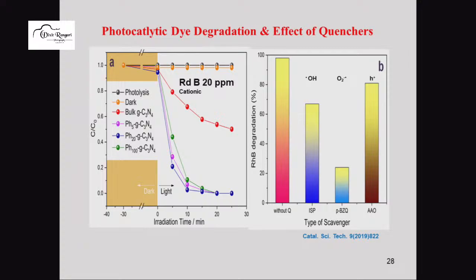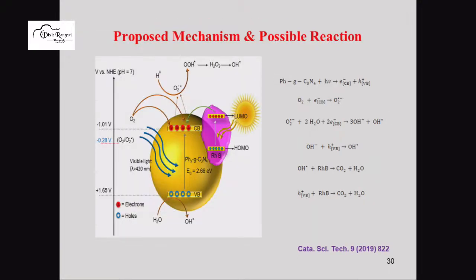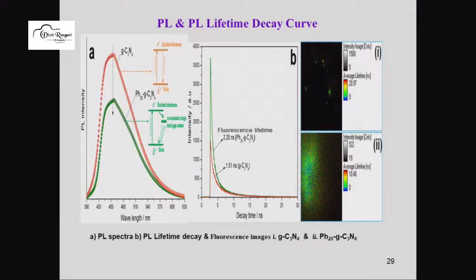And what are the species? The photocatalytic process involves different species: the electron, hole, hydroxyl radical, and superoxide ion. What are the species responsible for the degradation of these dyes? That can be determined by the quencher experiment, and this quencher experiment shows the presence of the superoxide ion as the major species for the degradation of the dyes. So again, this is the enhancement in the lifetime. The PL spectra shows there is an enhancement in the lifetime of phenyl grafted g-C3N4 compared to pristine g-C3N4.